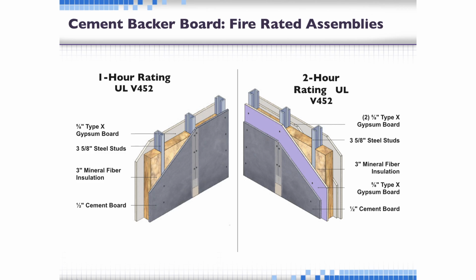We have a 5/8 available, but you don't need it for any specific reason other than you've got 5/8 drywall and you want to have a very smooth transition to the 5/8 cement board. But if you're sticking tile, that's not that big of a deal anyway. But anyway, so we have it available, but as far as codes, fire-rated wall assemblies, those kinds of things, we only need 1/2-inch board to pass our 1 and 2 hour fire-rated walls. One of the key things about it, though, is we do require the use of mineral wool in the cavity of the studs. So this is more of a commercial application, but if,